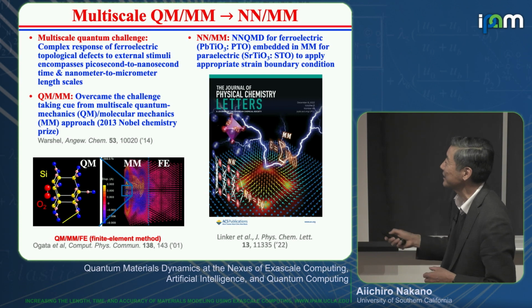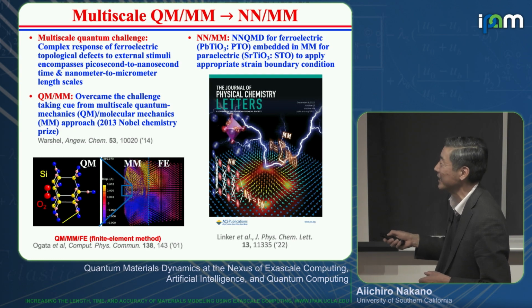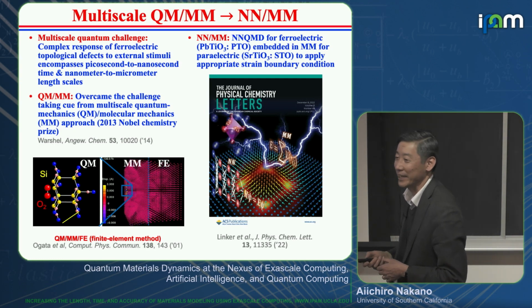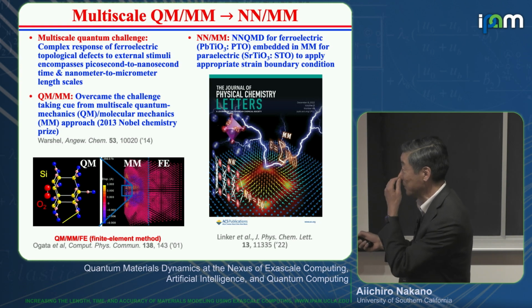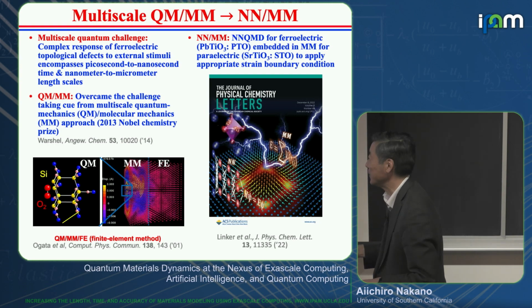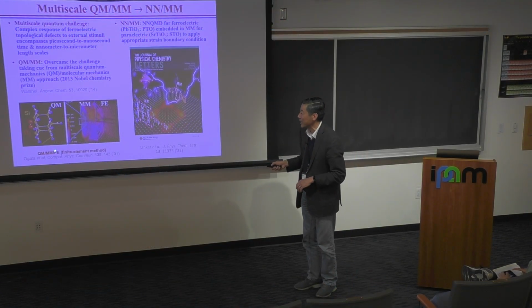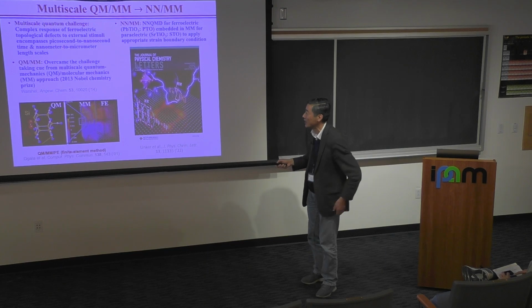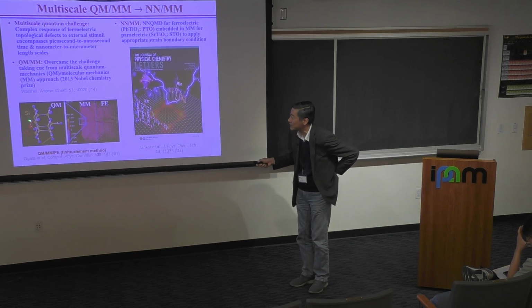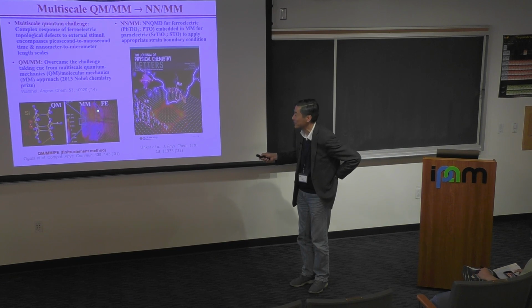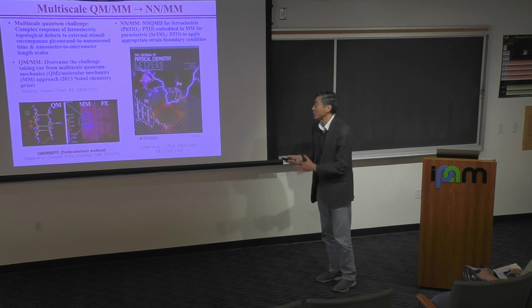So we solved this challenge taking a cue from the multiscale QM/MM, or quantum mechanical molecular mechanics method, for which my colleague Arieh Warshel got the Nobel Prize in 2013. In our group, we are also combining the multiscale QM/MM and the finite element FE method. This shows that the enormous dissociation energy of an oxygen molecule on a silicon surface is propagated from the small QM region to the bigger MM region to finally the finite element region, without noticeable reflection at the artificial model boundary. And so we have been doing this.